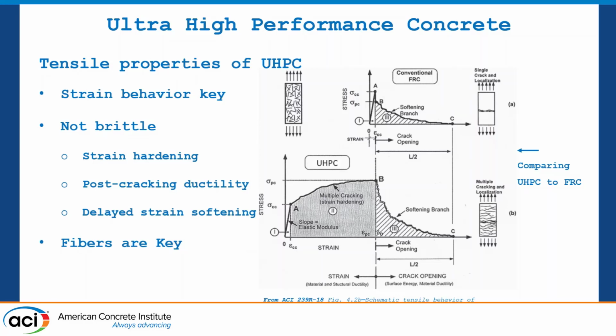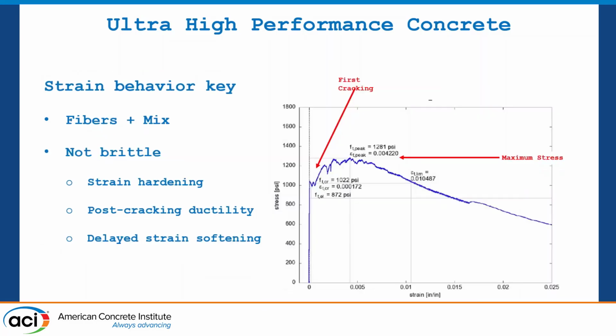With UHPC, you're going to get strain hardening first, and then delayed strain softening. So you're going to achieve your first crack here. You're going to continue to get additional load pick up, and that UHPC will be able to resist that load. You're going to get more strain hardening, and then you'll get this delayed softening failure. So that's really what sets UHPC apart. The reason that we're able to get that delayed strain softening and that post-crack ductility is our fiber content. It's extremely high strength in compression. Remember, it has extremely high strengths, and then we have high fiber content. That's what's going to give us this behavior. Fibers are key for that.